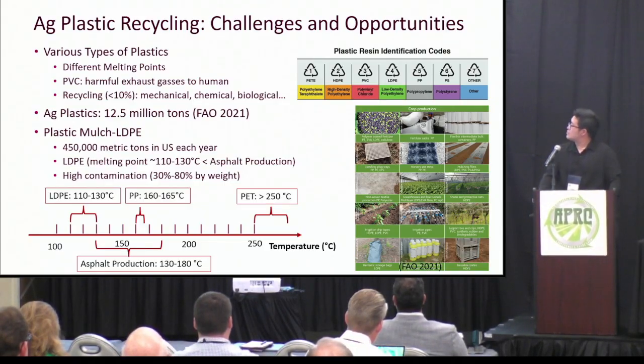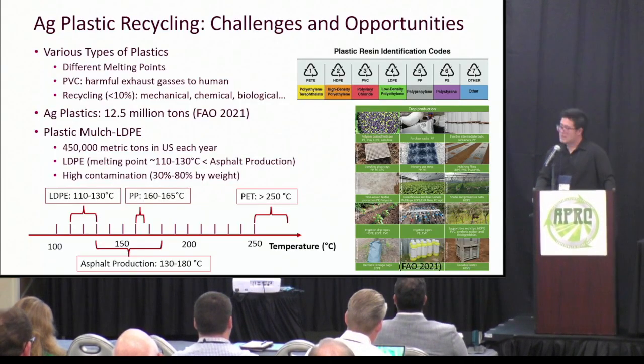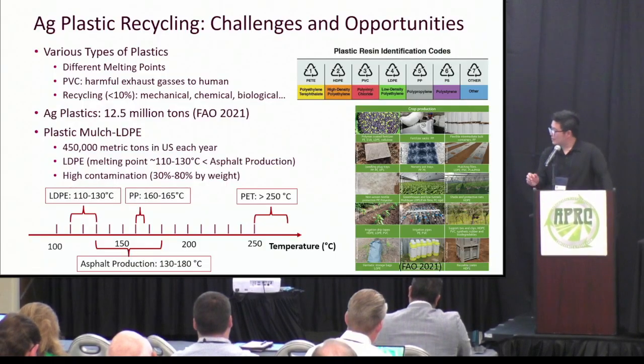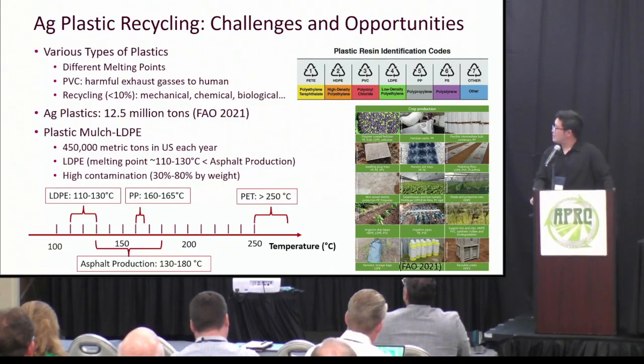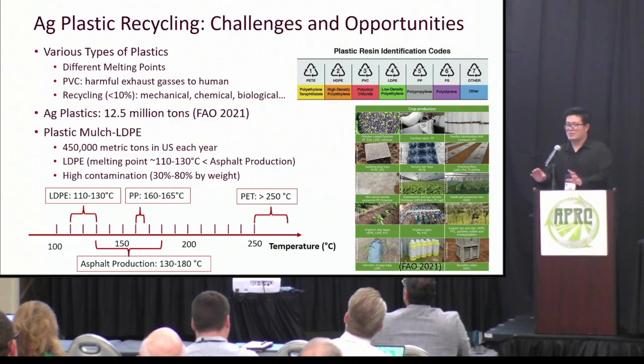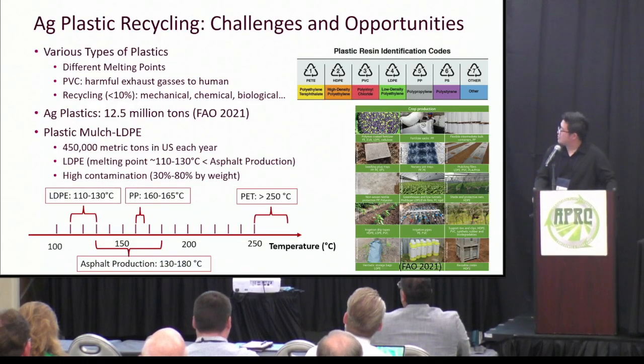So when talking about agricultural plastic recycling, there are different types of plastics, and different types of plastics have different melting points. For example, for LDPE, the melting point is between 110 to 130 degrees Celsius. The melting point is also a very critical property for plastic that will affect the compatibility with asphalt. And right now, the recycling rate is still very low, less than 10%. I think it's because of the very high contamination level of the mulch waste. The recycling methods include the mechanical method, chemical method, and the biological method. Worldwide, the amount of agricultural plastic is around 12.5 million tons. So that's a very huge number.